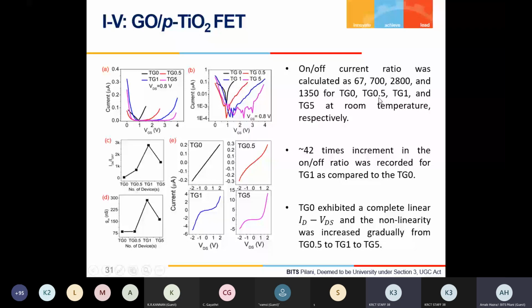So we are getting 2800, that is on the order of 10 to the power 3. If we compare with the literature, that shows an on-off ratio of 100. We are claiming we are getting a 2800 on-off ratio for our hybrid FET, and that has been represented here. The transconductance has also been calculated by considering the change of current with change of voltage, and that also shows quite an appreciable value.